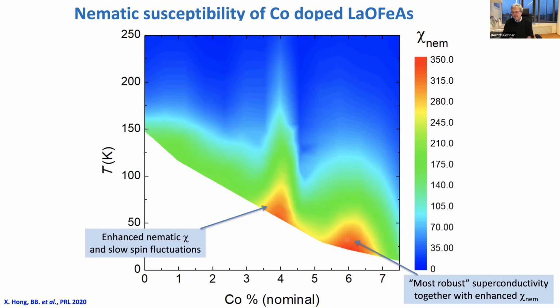Just taking the strain derivative of the resistivity, we can directly see the region where superconductivity occurs, with a maximum at about 6%. The other thing we see here is also a special point in the phase diagram, close to the region where magnetism disappears. And it's natural to assume that this is the coupling between nematic fluctuations and spin susceptibility, which we see there.